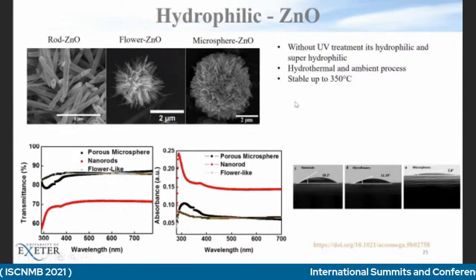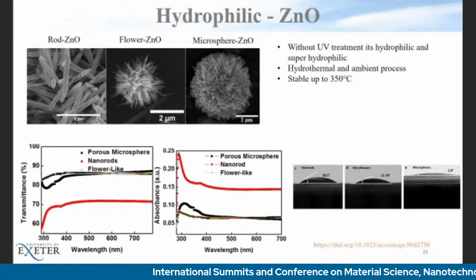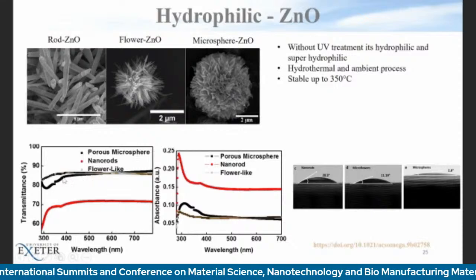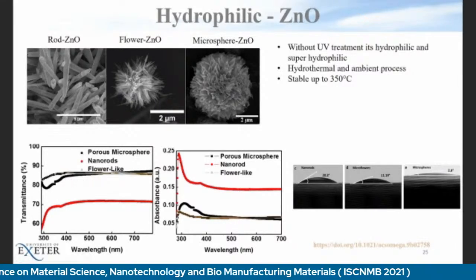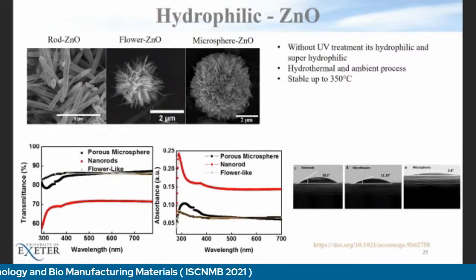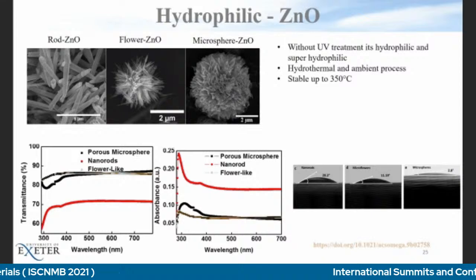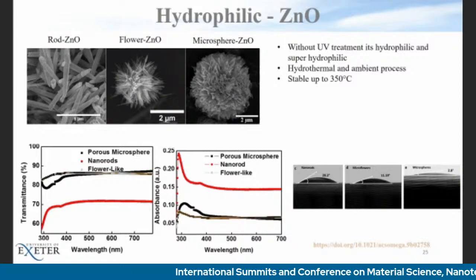To have that, we use a hydrothermal system, and we also found that up to 350 degrees centigrade, this coating is very much stable. And this is a very good point, because in general, when we do testing in the real-time field, we generally experience probably 100 degrees centigrade, not more than that. So this is a good work.